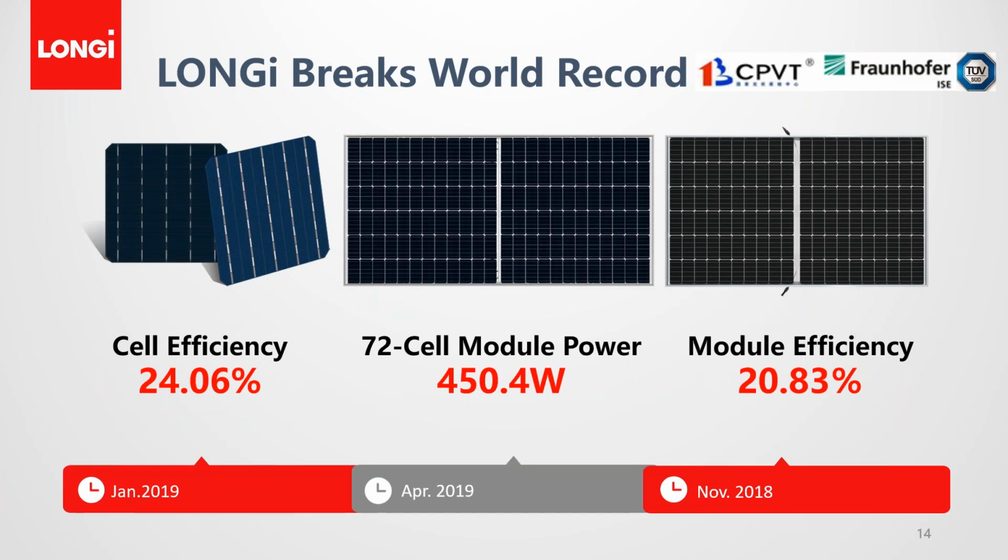For example, we are focusing on the P-type PERC product, P-PERC, monofacial and bifacial. At the beginning of this year, we demonstrated full size mono cell efficiency of 24%. This is a performance that previously could only be achieved by advanced N-type technologies. Now the gap in cell efficiency between P-PERC and the advanced N-type technology becomes smaller and smaller. We were also able to demonstrate module power output up to 450 watts and module efficiency of more than 20.83%. This is a testament that our consistent investment in R&D really yielded superior product performance.